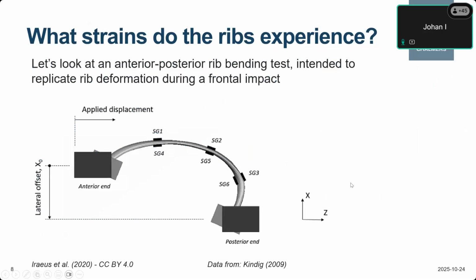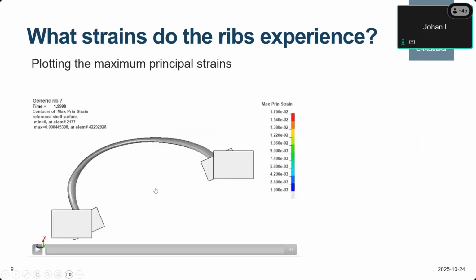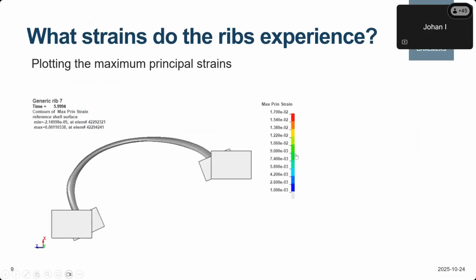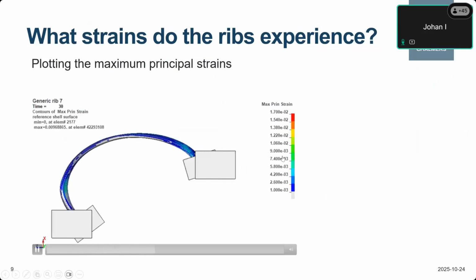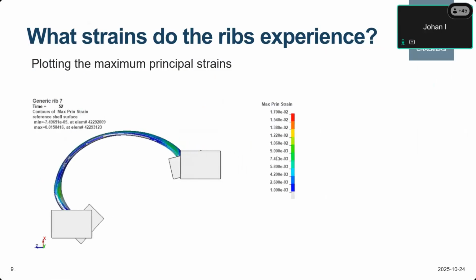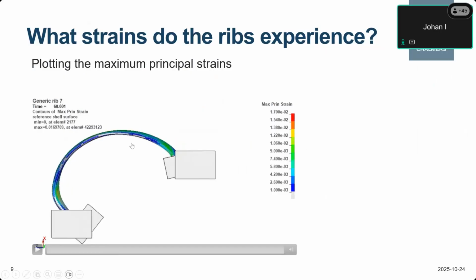If we do that, we can plot the maximum principal strains during that. This is a simulation of one of his tests for rib number 7. In this case, we can see that the maximum principal strain is about 1.7% at the end of the simulation, corresponding to when the rib fractured in reality. And I would say that 1.7%, based on the risk curves we have, is kind of the onset of fracture risk for older subjects.